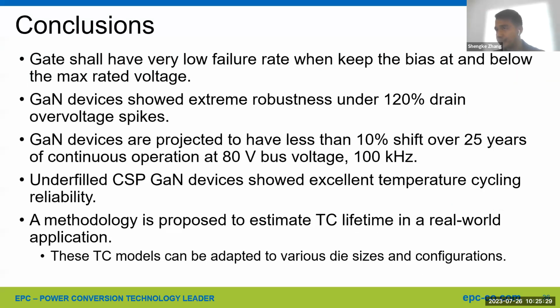Okay, so conclusions. We have discussed gate, drain, and temperature cycling, three reliability stressors. On gate reliability, the gate should have a very low failure rate when we keep the gate bias at and below the max rated gate voltage per data sheet. On the unclamped inductive switching testing result, we show that GaN devices have extreme robustness under 120% drain overvoltage spikes. We tested up to 10 billion switching cycles on our 100 volt eGaN devices.